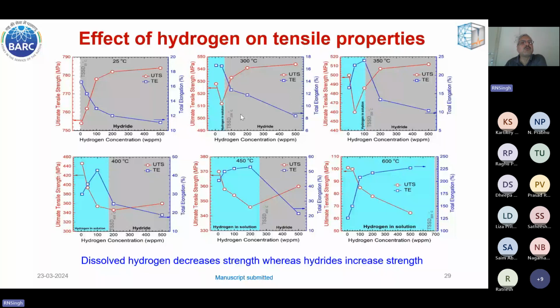Lots of curves are there, but if you see, the ultimate tensile strength and total elongation are plotted here as a function of hydrogen concentration. And this boundary you are seeing, the cyan-colored boundary, is changing because the test temperature is changing from 25 to 300, 350, 400, 450, and 600. As a result, the dissolved hydrogen concentration is changing. As I said earlier, in a hydride forming metal, depending on the test temperature, part of the hydrogen will be present in solution and part of the hydrogen will be present as hydride. So the cyan color is the region in which hydrogen is present in solution, and this dark color is the region in which hydrogen is present as hydride.